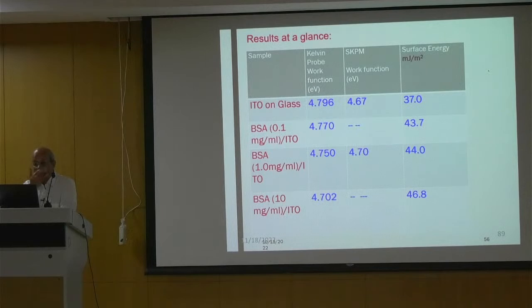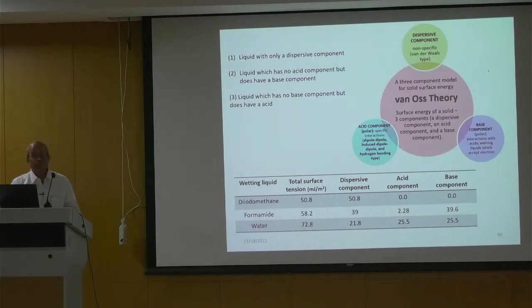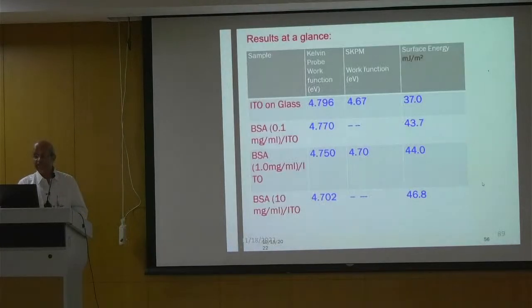So yeah, I think the same picture. This tells you how the protein is going to affect. For example, Kelvin probe work function is 4.796. Of course, we have seen 4.67, and we have measured the surface energy of this ITO on glass. How do you measure? Standard methods are available. This method is what is known as van Oss theory. You take three liquids, and from these three liquids you take the contact angle. By calculating from the contact angle you get the surface energy. When the surface energy is 37, the Kelvin probe work function is 4.79, and the other technique has given 4.67.